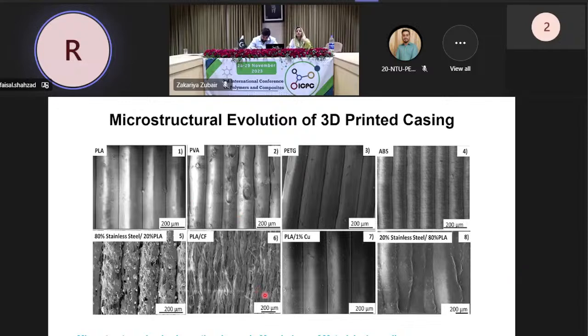So this is the microstructure. We have printed the material, and we examined the microstructures of the different filaments to see how they look, because the printing layer is very thin, 0.1 to 0.2 mm thick. We want to see exactly what the material looks like. You can see the different materials have different morphology: this is PLA, PVA, PETG, ABS. But when we introduced stainless steel and carbon fiber, the morphology of the printing material changed. This is just 1% copper with PLA, and this is 20% stainless steel with 80% PLA.